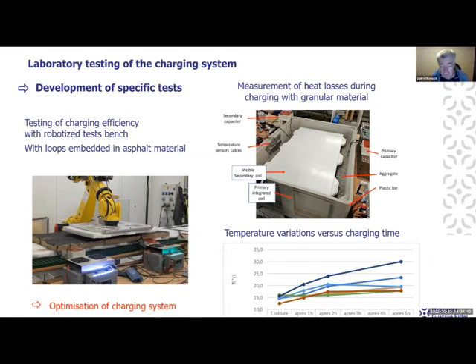We did different tests with different distances and different positions of the coils, also with dry and wet material. During operation, we measured the temperature variations at different points with temperature sensors. And we found that in the laboratory, there was a very significant temperature increase when the system was operating, reproducing charging cycles which would be representative of charging of vehicles on the road. We found temperature increases of 15 degrees after several hours of operation.